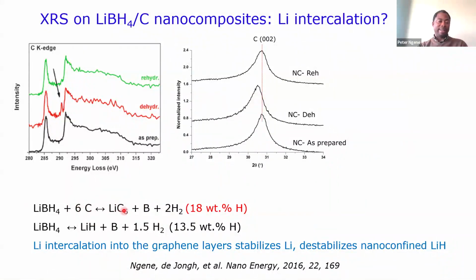And because the lithium borohydride is very close to the carbon, you form LiC6, which is already known in batteries, that you can intercalate this. And that is the only way you can actually get 18% hydrogen, which we saw in this other material. So this is something that we learned from doing this X-ray Raman scattering. Even though we thought then it wasn't really what we wanted, because we didn't see evolution of phases. If you just heat it up, you see that the phase changed immediately. So we couldn't see what the evolution of the phases was.